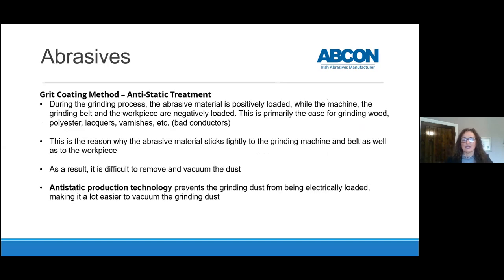So it does mean that this would account for why some materials are more expensive than, say, the grit coated materials. Just wanted to tell you a little bit about anti-static treatment as well. So during the grinding process, the abrasive material is positively loaded, while the grinding belt and the workpiece are negatively loaded. This is primarily the case when you're grinding polyester lacquers, varnishes, materials that are bad conductors. And it's the reason why the abrasive material sticks tightly to the grinding machine and to the workpiece. As a result, it's difficult to remove and difficult to extract or vacuum the dust.